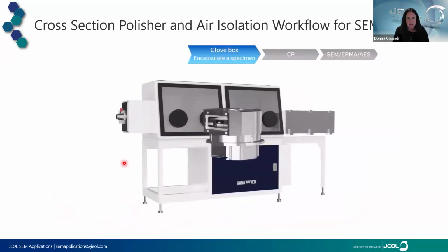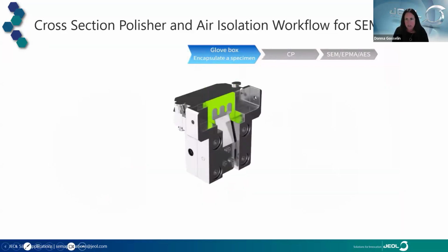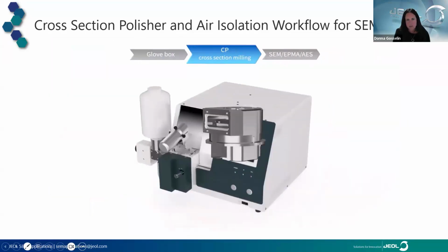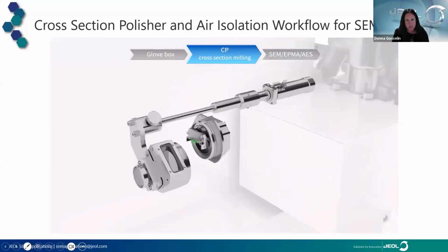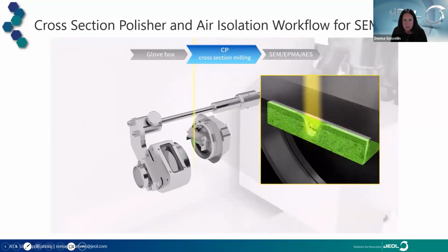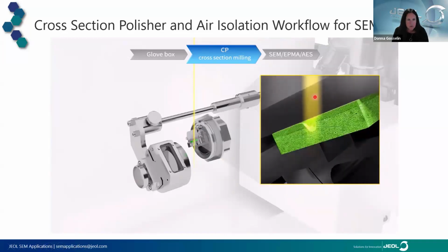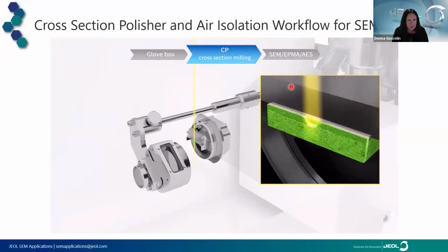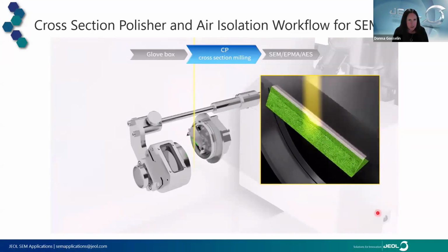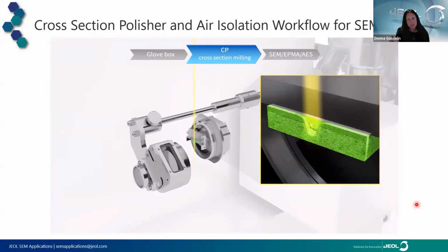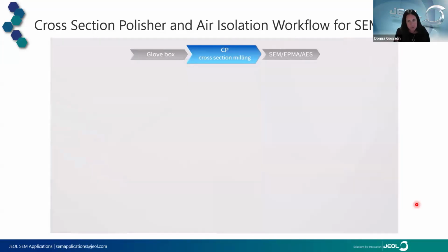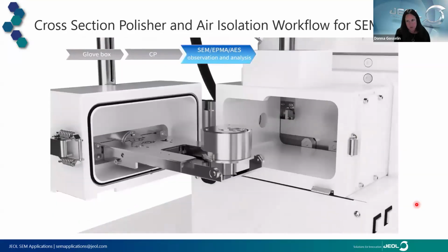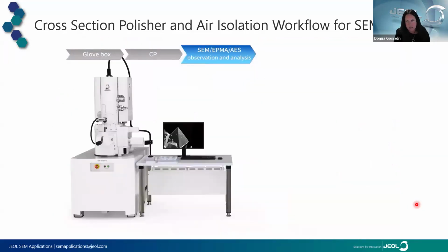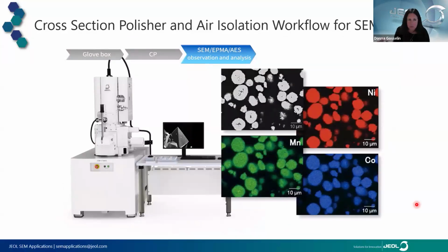So let me just start this. The sample is mounted in our transfer vessel in a glove box and then brought to the cross-section polisher. Once the chamber in the cross-section polisher is fully evacuated, we can open the cap. The cross-section is then made by exposing the sample to the argon beam. Here's an exploded view of the shielding plate that masks the sample. So only the area that's protruding from that shielding plate is milled away. The width of the cut is typically about 1 millimeter, and the depth will be dependent on the milling time. The specimen stage was rocking, and that minimizes any curtaining effects for a nice smooth cross-section. And on completion, the cap is placed back on, and this transfer vessel is brought to the SEM to continue with your imaging or analysis.